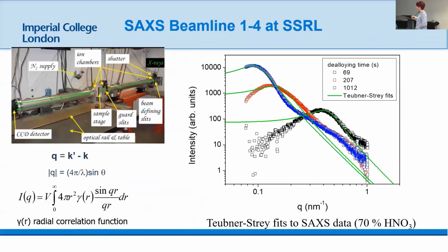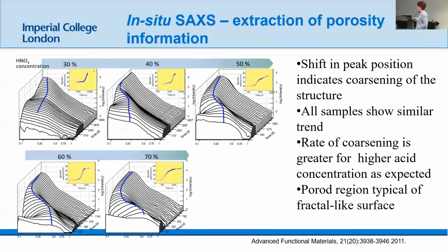So to correlate that directly to the particle or the porosity, we did some SAXS data. And again, you see these self-similar repeating trends across the different sizes. We see fractal-like surfaces and a shift in that position that tells you it's coarsening.